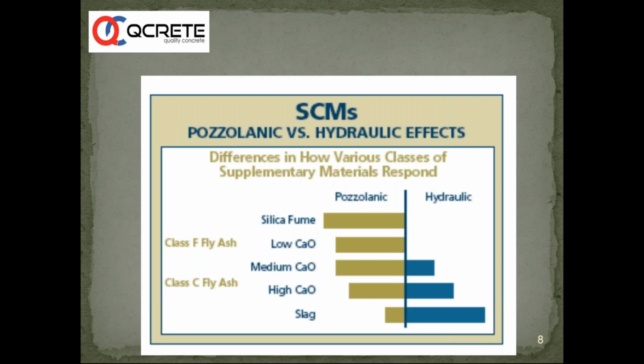So we need to know that when these materials are more towards pozzolanic, they don't directly react, and they have a high shelf life, and they are not affected by moisture. Even if we put some amount of water into this, it will not become hard, and they will react only in the presence of cement or any other kind of activator.